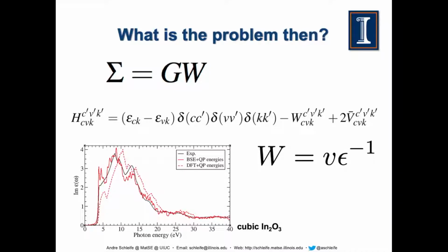We've seen similar trends for many of the other oxides. Every time we go to the absorption onset, or we look at an exciton binding energy at the absorption onset, we overestimate the strength of excitonic effects in our framework. So we started questioning, because we don't really have knobs in the framework that we can tweak. We're trying to figure out what we are missing. I'll show you two examples where this epsilon is indeed the quantity that needs to be improved.